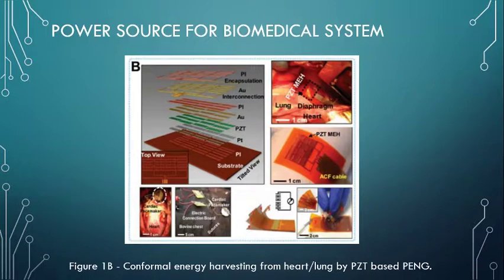During cardiac contraction and relaxation, the conformal contact of the whole device with the heart without any destruction was of significant importance for in vivo applications of the energy harvester. The output voltage was up to 5 volts, greater by 3 orders of magnitude than previous in vivo results, when the in vivo PENG was attached on the right ventricle of a bovine heart.